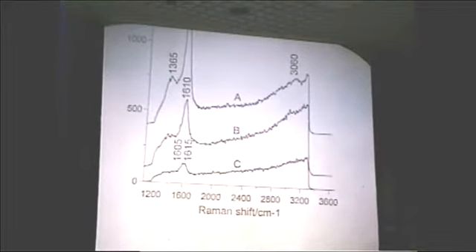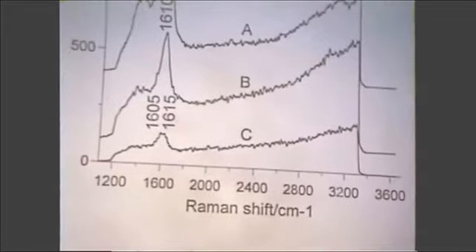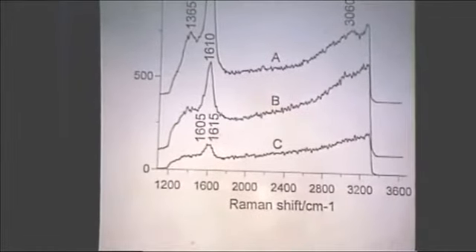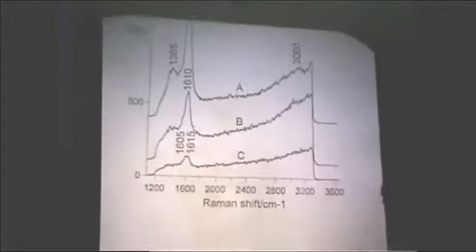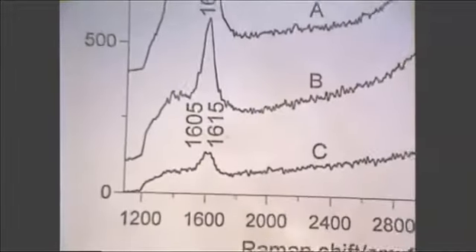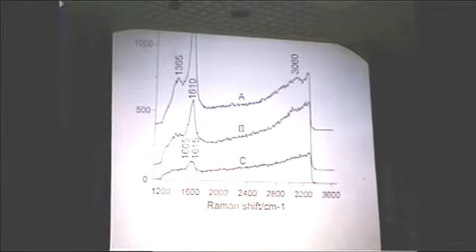Now, I showed these data to Bob Byerline when he came to visit us last fall. And Bob, when he was at Amoco, did some Raman studies of coke. He was very interested in the positions where these bands showed up, and the fact that they seem to end up in an aromatic structure with only a few rings fused together. So his thought, which seems reasonable to me, is that when you burn this coke, the graphite planes burn preferentially from the edges, so that the graphite planes are shrinking from the edge. And what you ultimately end up with is some planes which for some reason are not attacked by the oxygen. Either they're inaccessible or they're bound in some interesting way so that they are not oxidized.